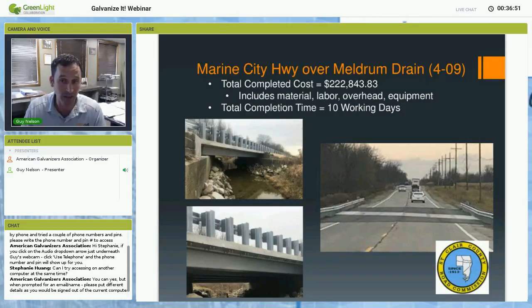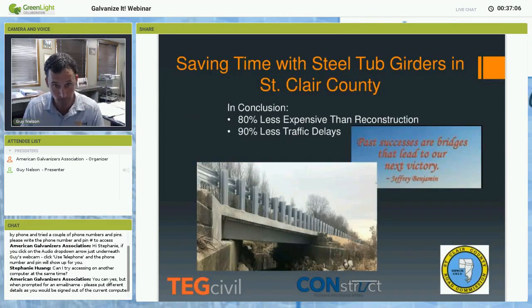So 2 bridges done basically in a period of a month, with 2 full road closures of 10 days each. The county was very happy with that limited amount of closure on this very busy roadway. And then in conclusion, the superstructure was 80% less expensive than it would have been for the DOT to come in and completely replace these. That's based on a reconstruct fee of a little bit over $1 million, and we spent near $200,000. So we spent 20% of the funds to get a reconstructed bridge with a 60-year plus service life.